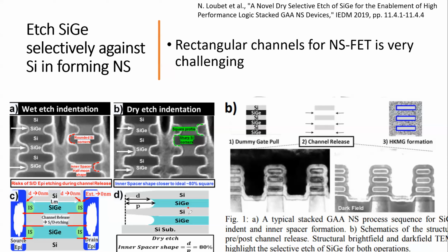Because silicon is only about 5 to 6 nanometers. If it's too thick, then the device cannot control. If it's too thin, the VT cannot control. Anything under 4 nanometers, you cannot control it. And over 6 or 7 nanometers is kind of useless. So you're controlling 5 or 6 nanometers for each layer. And this is not an easy thing to do. But of course, people have done it. So this is no problem already.